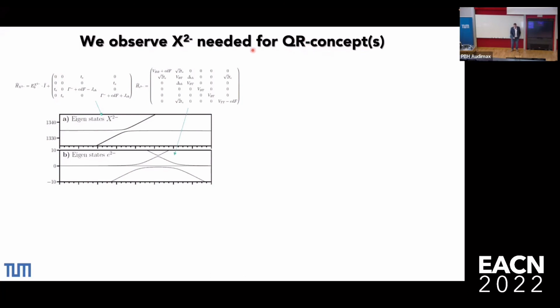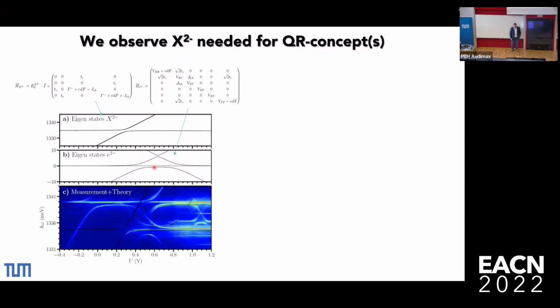So this is the trion state versus electric field. This is what you leave behind. That's the 2 electron state that I showed you a couple of slides ago. And the difference in energy between these two states, that's the photon energies that we obtain. I don't know if you see it on the screen better than I see it here, the black lines are theory and the experimental data is behind. So there's great agreement between the two of them.